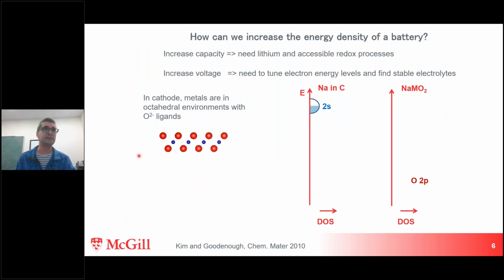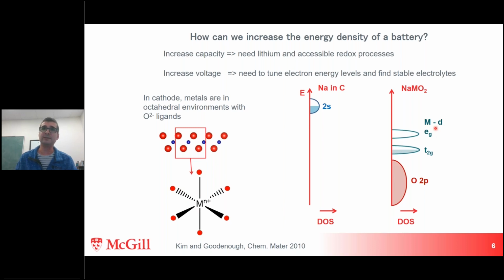So how do we increase energy density? Well, these are layered oxides. So you have this transition metal with oxygen above and below. This is the layers that I was showing at the beginning. This is actually an octahedral environment. So we have these d bands of the transition metal that are split, and the Fermi level is normally in a t2g. So when we take sodium from the cathode and put it into the anode, we're also taking an electron and moving it by the external circuit. And the electron has this energy, or change in energy, as it goes from the cathode to the anode. And that change in energy is our voltage.